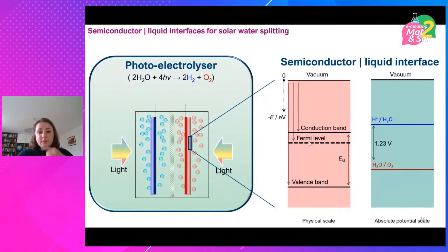And what we discovered, because we were unable to do this, was that I kept calculating the flat band potential of hematite as way positive of the conduction band, whereas it should have been more negative so that it would actually lie between the conduction and valence band. And I thought, well, either the conduction band energy is wrong, which may well have been the case, because as a first attempt, it's estimated based on electronegativities of the constituent atoms and just an assumed average band gap. But the flat band potentials were so high above the conduction band that if it was true, you should have probably seen spontaneous hydrogen evolution happening on hematite. And we know that that's not the case. So being completely unable to align these scales confirmed that there was something really missing in this picture.